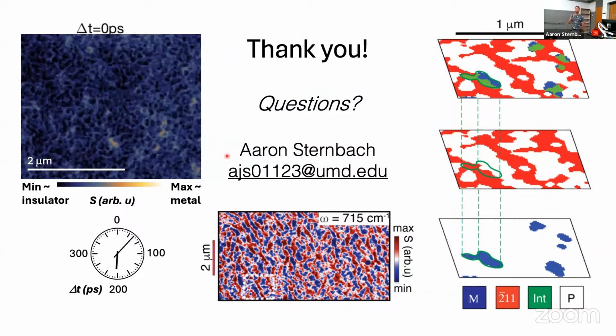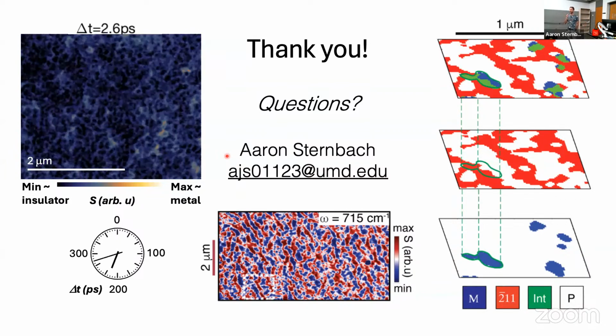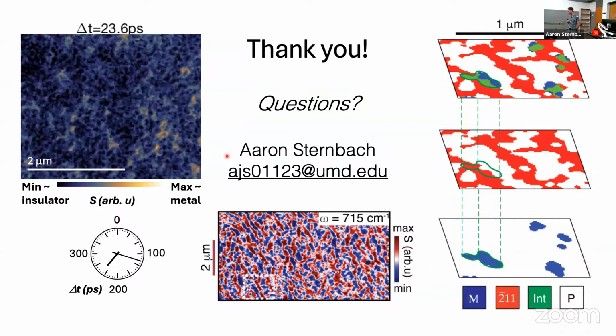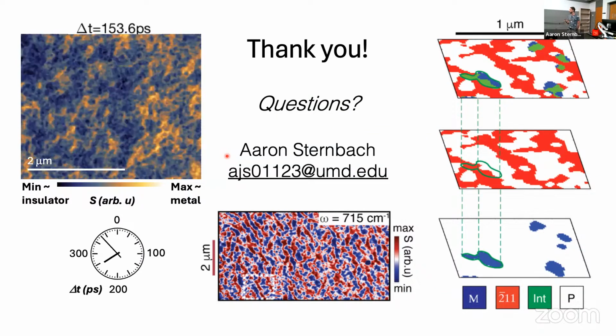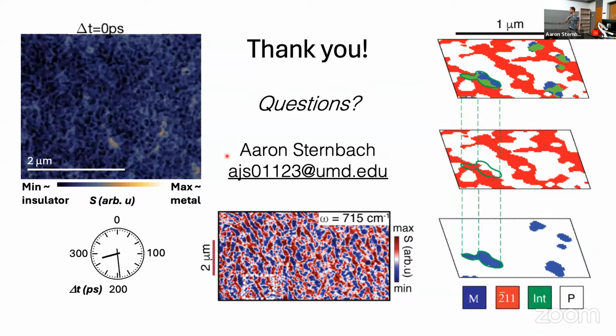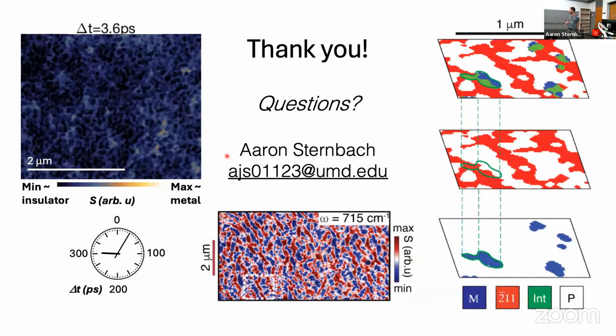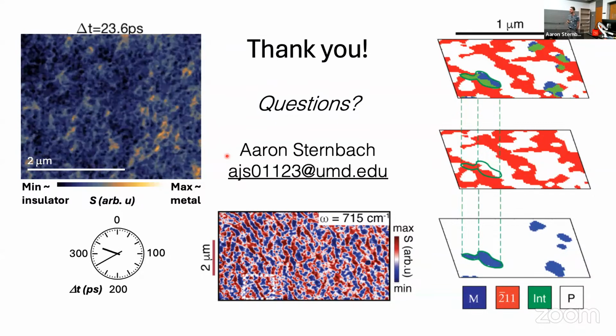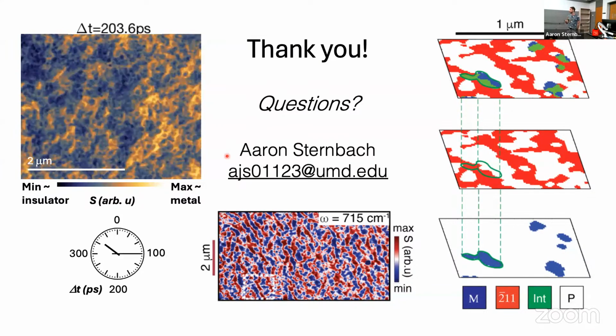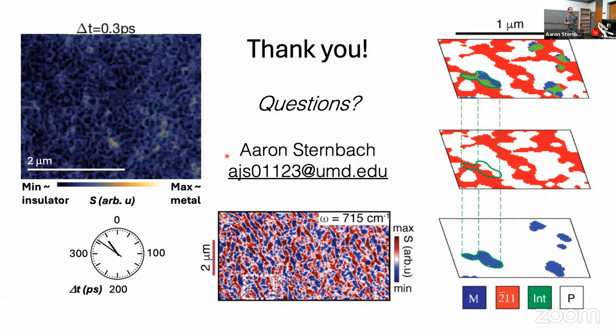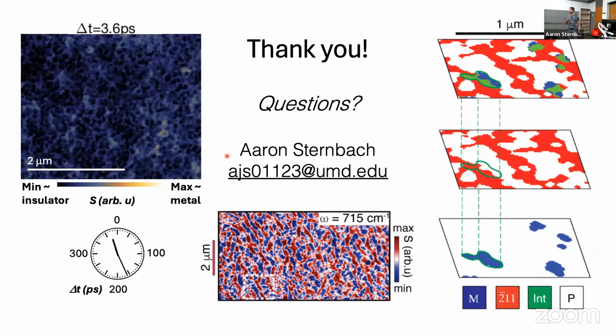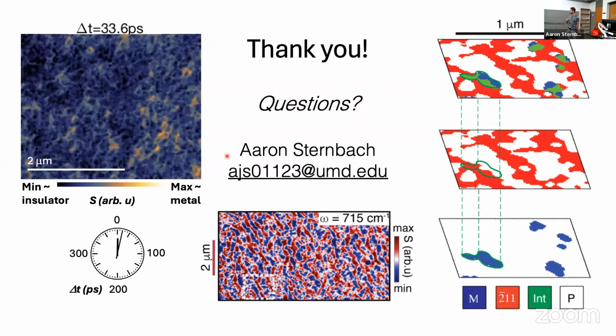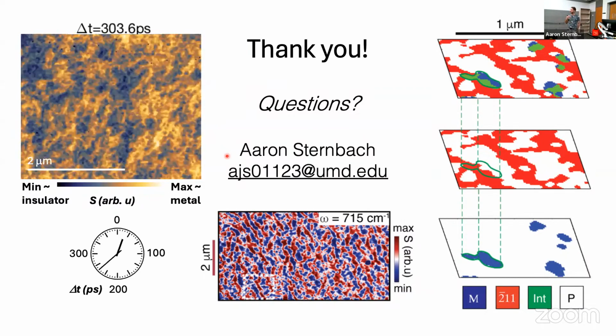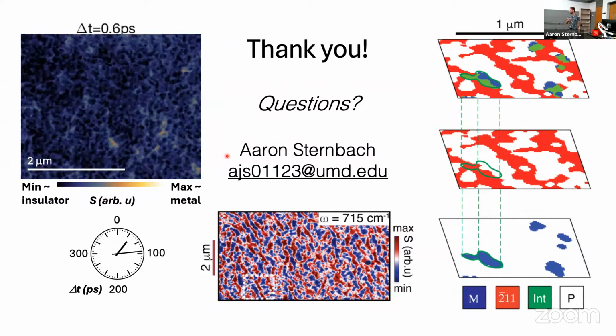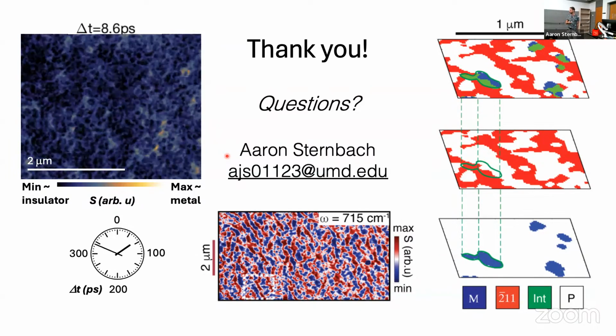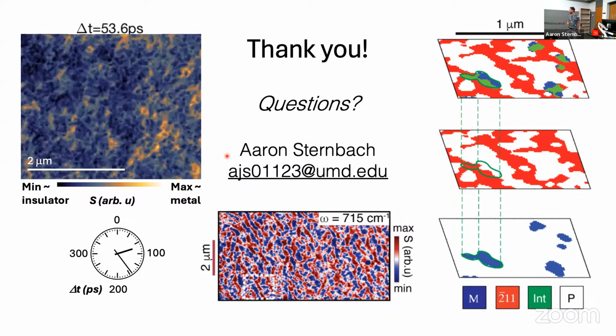Yeah. So this is already formed. This is part of just this film, and it depends on the growth conditions. In C-cut sapphire, the surfaces are less rough. In TiO2, you can get nearly single crystalline films, and there are bulk crystals that don't have these grains at all. The reason that we studied this was that the sapphire serves as a good heat sink. In a lot of these other variations on the film, heat stays in the system for milliseconds, and that makes it very challenging to do near field measurements because you'd have to work with sub-kilohertz sources.